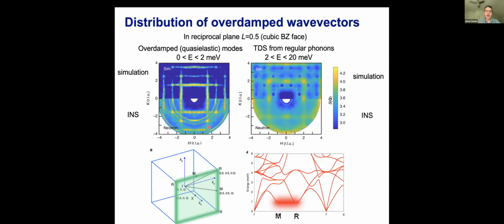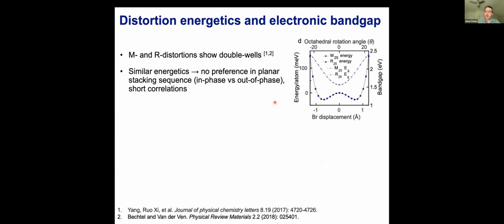And using our modeling, we can actually reproduce the diffuse scattering as shown in the top half of these panels compared with neutron data. We see the sharp rods at low frequencies and the more conventional thermal diffuse scattering at higher frequencies. We can also use the modeling to understand why these materials do this. In short, this arises because of their unusual anharmonic potential energy surface and a competition between these two types of distortions that have very similar energetics in our simulations, and also large amplitude fluctuations with well depths that are consistent with the phase transitions being around room temperature.